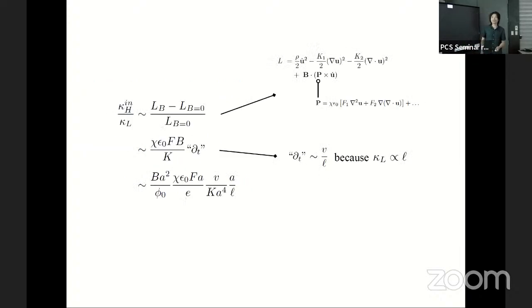Let's see, roughly speaking, why that is the case. So let's compute the Berry curvature. Let's estimate the Berry curvature contribution to the Hall angle, the kappa H over kappa L. And it turns out that the estimation is right. Even if you do the actual calculation, it agrees with this estimation. The Hall angle due to the Berry curvature will be proportional to the time reversal odd part of the Lagrangian versus the time reversal even part of the Lagrangian.